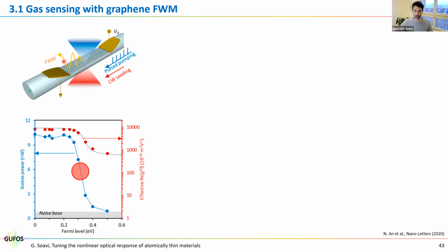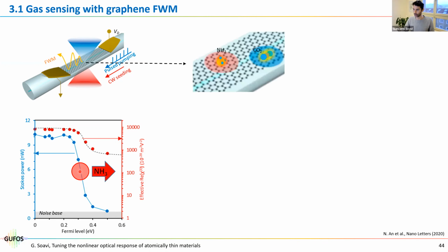Then we apply gold contacts, and with these gold contacts, we will be able to modulate the Fermi energy. Now, we fix the Fermi energy at this point, because this is the point where we have the largest change in the four-wave mixing efficiency for small changes in the Fermi energy. So this is where we have the highest derivative, so to say.